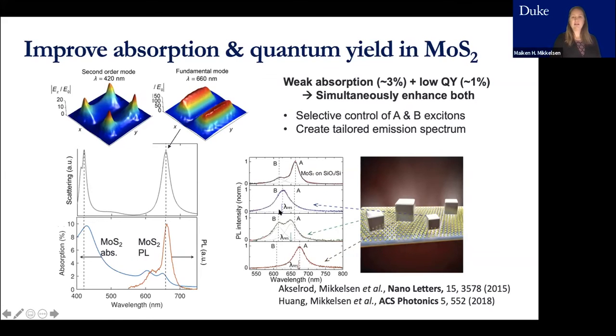The little arrow here is indicating where we put the plasmon resonance. And in this case, we could enhance the A exciton a couple thousand times, but the B exciton about 6,000 times. This is because the B exciton intrinsically has a lower quantum yield, and when we enhance it with a plasmonic structure, we're enhancing the quantum yield to be about the same in both cases, at around 50%. So that means we can enhance this weaker B exciton more. So I think it's exciting to see how you can use the plasmonic structures also potentially to study even weaker exciton states in two-dimensional materials.